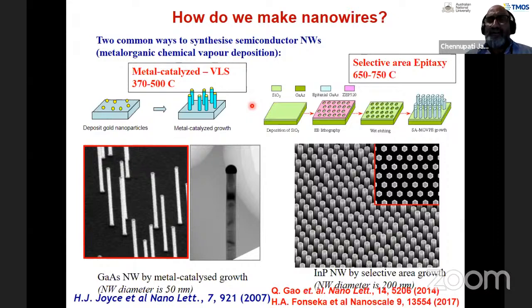If you keep on mixing more and more sugar, above the solubility limit of the sugar, sugar crystals start precipitating out. The same physics is happening here as well. In fact, this is the work of my former student, who is now an associate professor at Cambridge University, Dr. Hannah Joyce. She developed a technique called a two-temperature growth process, where she was able to demonstrate we can get really beautiful cylindrically shaped nanowires with no defects whatsoever.